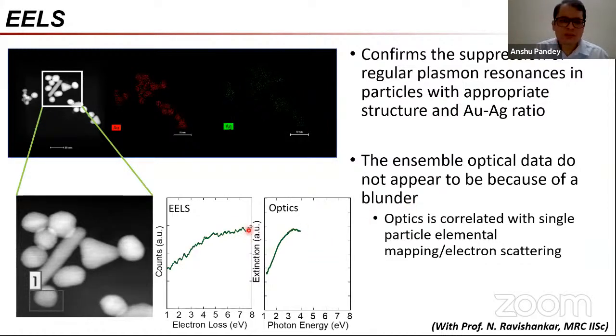So we might worry that the optical data is simply a blunder of some kind, but then EELS says the same thing, and it appears on a single particle level, because EELS also lacks resonances which are at least apparent. Again, there is no light absorption per se happening in the case of EELS. There are no significant electron loss resonances appearing in EELS, at least for lower energies.